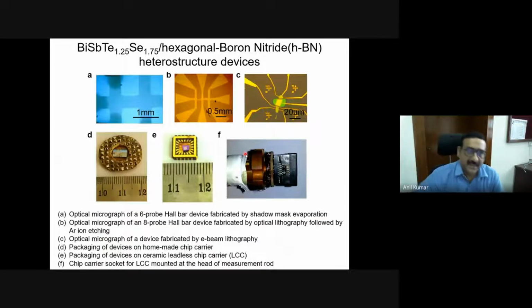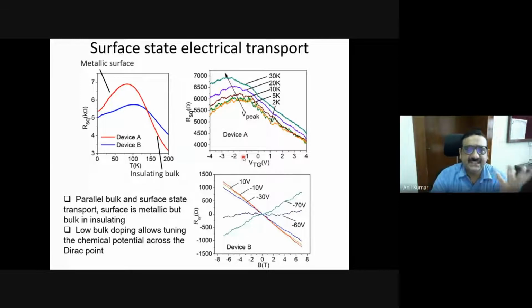For the first property, you make this device and then do wire bonding to a chip carrier. This chip carrier is inserted into this holder, and the whole system is dipped into a liquid helium system, so that you can cool it down to 2 Kelvin and then do temperature variation and different kinds of measurements. Let me tell you the kind of results you're getting. For example, if you vary the temperature of this material and measure the resistance, you see that the resistance increases in the beginning, goes through a maximum, and then starts coming down.